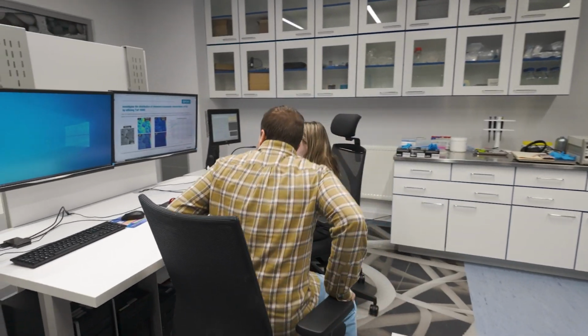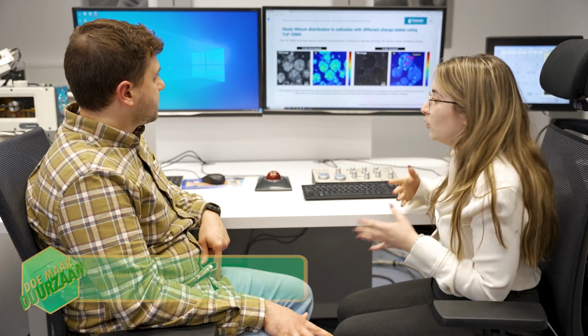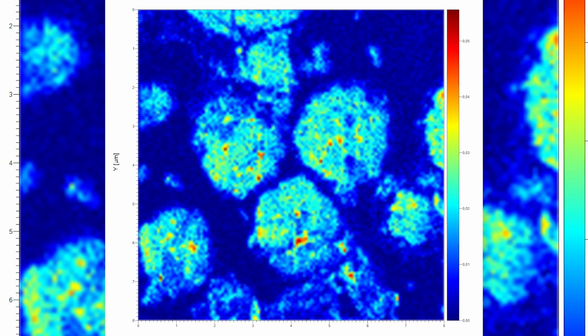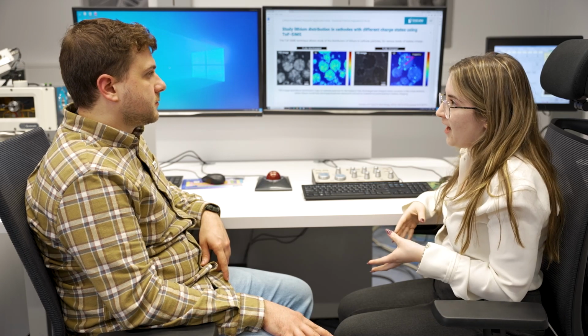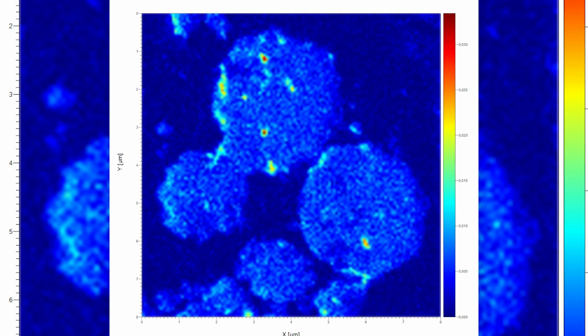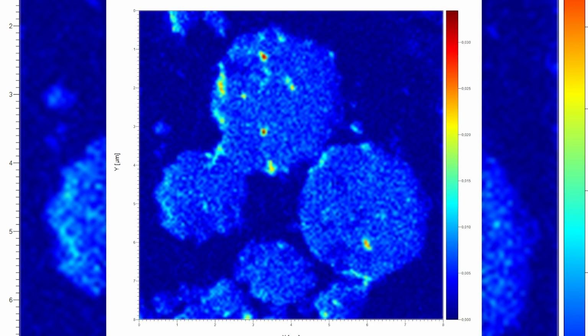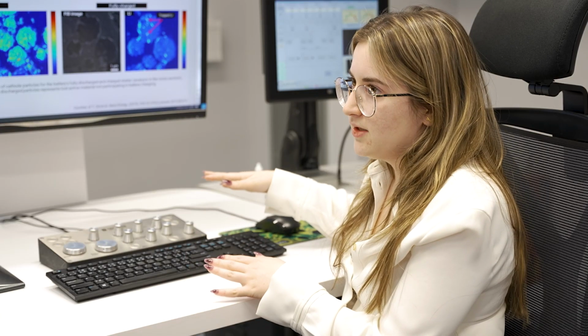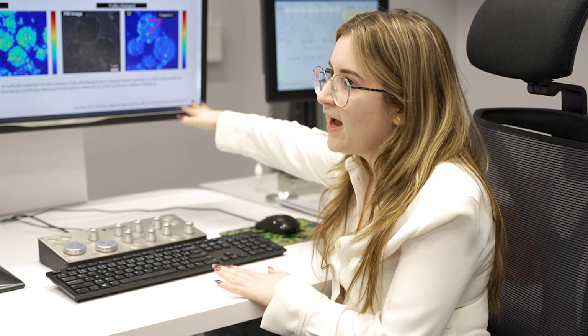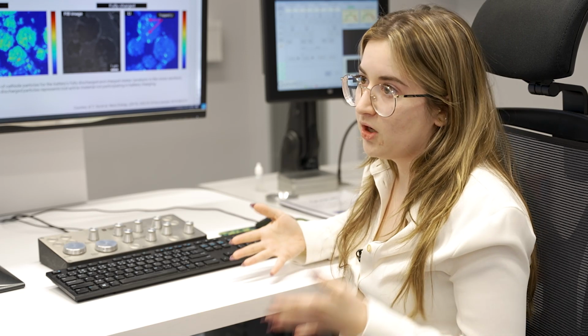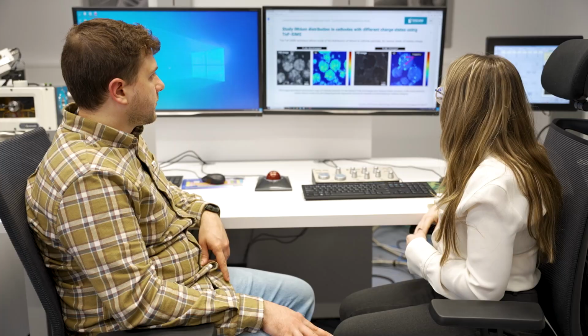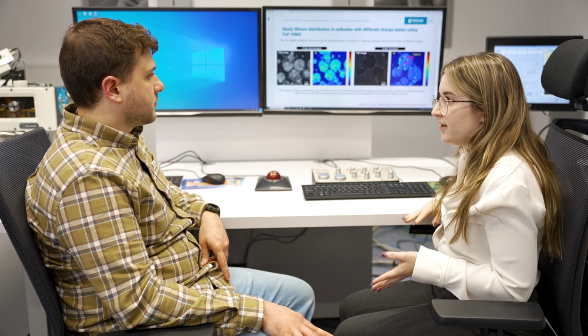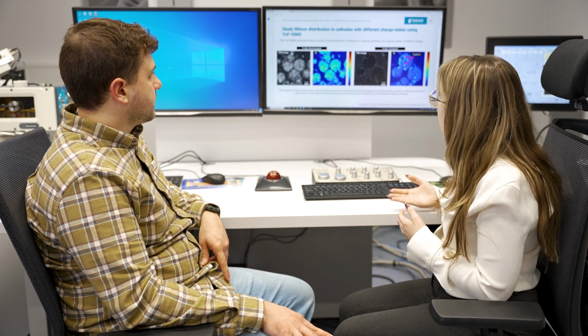So what we're looking at here are two data sets, one of a fully discharged cathode and one of a fully charged cathode. On the left, we have a fully discharged cell. What that means is all the lithium should be in the cathode. On the right, we have a fully charged cell, and that means theoretically that all of our lithium ions should be in our anode. TOF-SIMS allows us to see that we actually have lithium trapped in our cathode, and we're not fully utilizing our lithium economy in the way that we want to in our battery. This is really useful in post-analysis of batteries because it allows us to link our analysis with our cycling data.